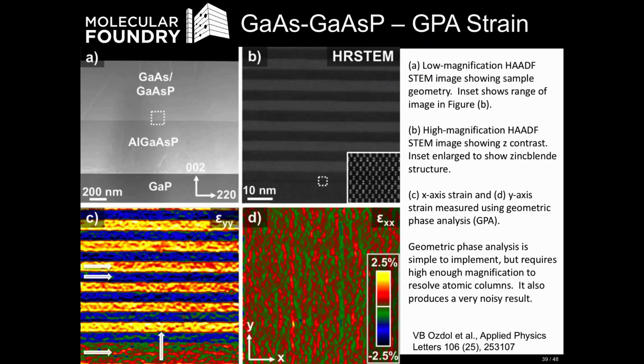This is what a conventional geometric phase analysis, or GPA, strain analysis looks like on a simple semiconductor sample. So on the left here, you can see the overall dark field geometry. We have a gallium phosphide substrate, an aluminum gallium arsenide phosphide film, and then a lattice matched gallium arsenide phosphide sample on the upper part of it there.